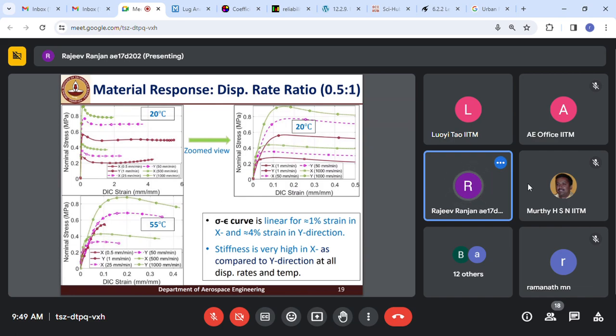However, for this particular displacement rate ratio, it was observed that the stress-strain response is linear only up to 1% strain in the x direction, and it was the same value as we observed during equibiaxial, which is 4% strain in the y direction. This is happening because the displacement rate in the y direction is double that of the x direction. So the material is getting strained at a faster rate in the y direction, and when actual visible damage starts showing in the stress-strain response, the strain in the y direction is around 4%, but since the displacement rate in the x direction is less, the material becomes non-linear from 1% strain itself.